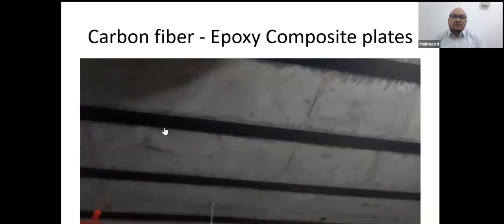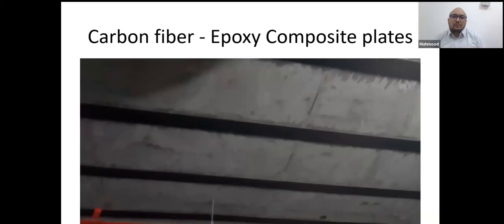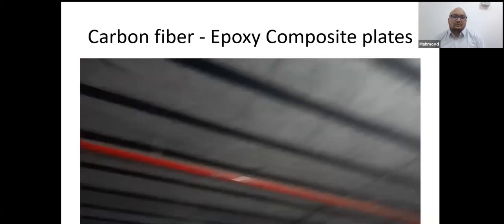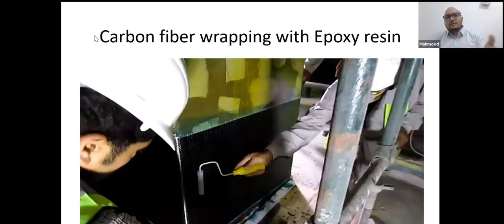They make the surface smooth. They apply an epoxy based adhesive. Then they fix the carbon fiber plate, the laminated plate, to strengthen the structures. For the columns, they use carbon fiber wrapping with epoxy resin.